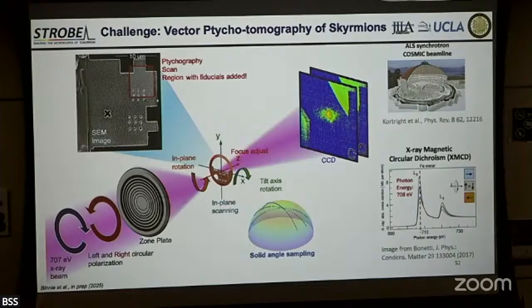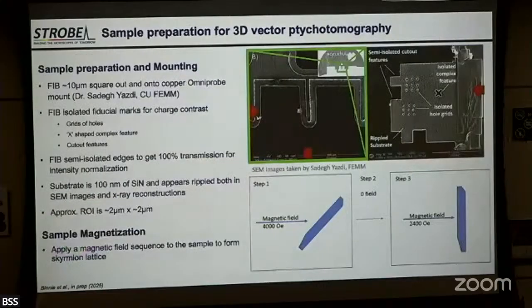But again, after a 4-year effort, this is the third sample where we finally figured it out. We first thought that the edges might be enough to do the tomographic alignment, but it turns out they're not, because they're not perfectly sharp, and when you do X-ray imaging, you can have carbon buildup. So you have to have other things as well. We have a master person in charge of our electron microscopy of materials facility. So he was the one who did this,